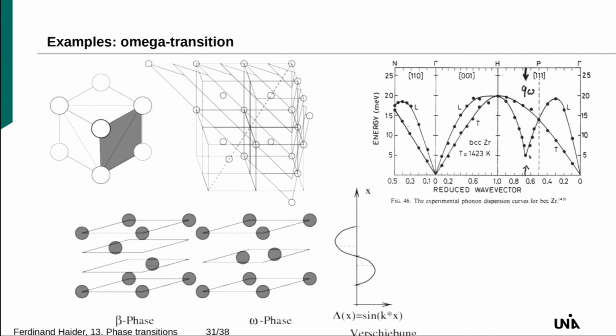And you see that there's a minimum here. So this means that such an oscillation here, at elevated temperature, requires only low energy, and if you go lower in temperature, this goes to zero, and then you have this transition here.